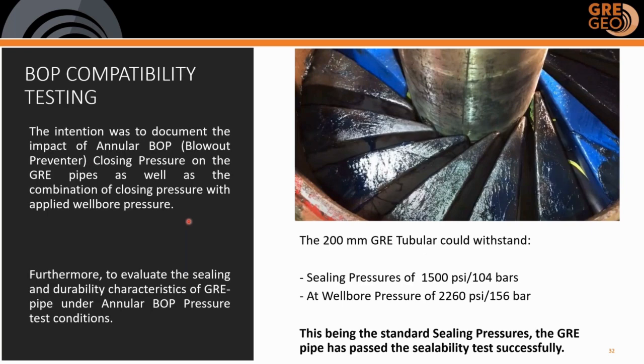The BOP testing was done in two cases. We first tried to seal off the pipe and see how much pressure it can withstand. As you may see, the sealing pressure reached up to 104 bars, which is the standard testing pressure. At well pressure, we then tried to increase the pressure even further, and it can withstand up to 156 bars. Thereby, it has withstood the standard procedures for the shut-in and seal compatibility of the BOP test.